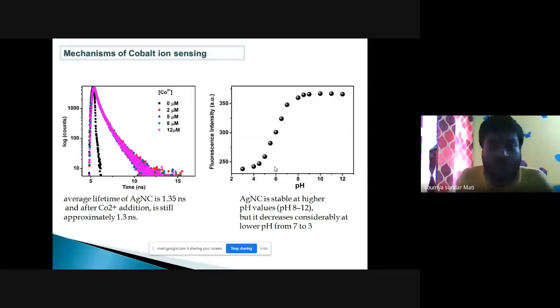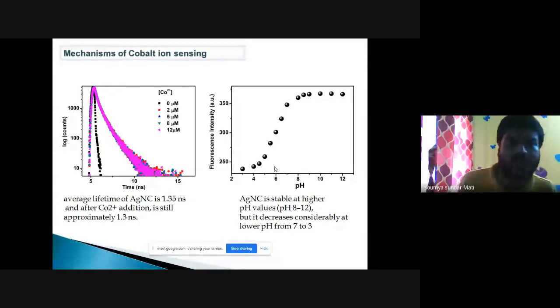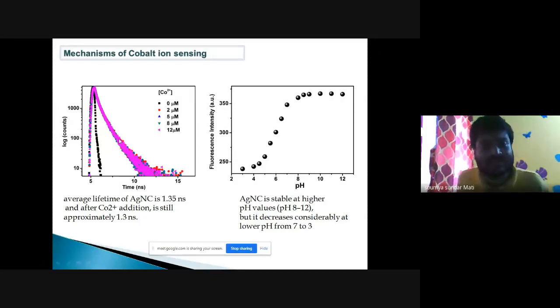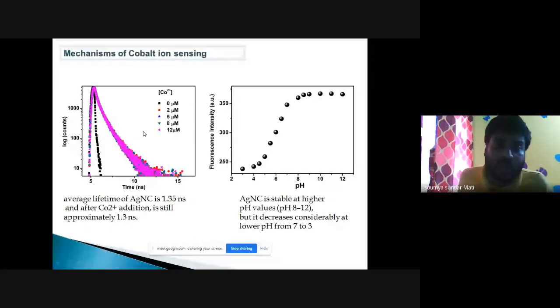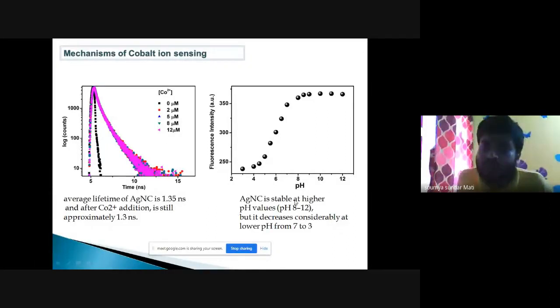We have to apply the lifetime and pH measurement. Lifetime measurement of silver nanocluster shows that consistent addition of the cobalt 2 plus ion does not change the lifetime of silver nanocluster, 1.35 nanosecond. And this inferred that the energy level of silver nanocluster does not interact with cobalt 2 plus ion. And in case of pH study, upon consequent addition of the H plus ion in the pH range from 3 to 7, that is the higher acidic region, the fluorescence intensity of silver nanocluster decreases, as observed in case of cobalt 2 plus addition.